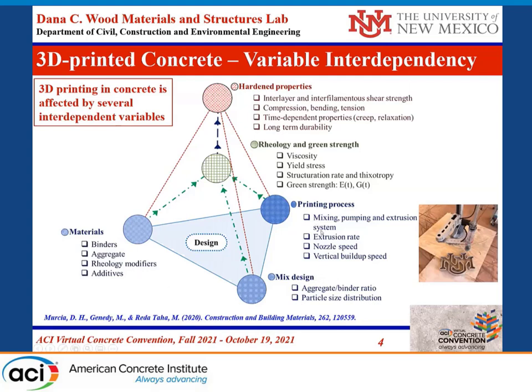What many presenters today are discussing is the printing process and simulating it, trying to predict what is going to happen and the most economic way to do this printing process, including the mixing, pumping, extrusion system, extrusion rate, nozzle speed, and vertical buildup speed. These factors interact to affect the rheology and the green strength of the material — the strength of the fresh concrete that is able to be built up to make the shape and resist stresses.